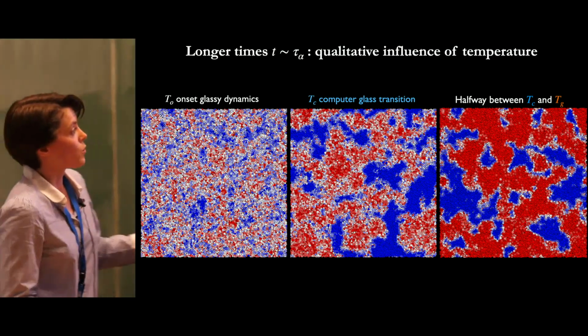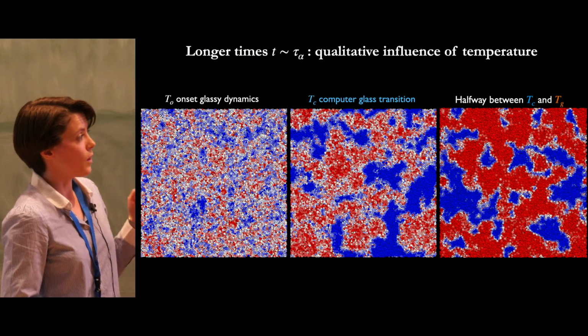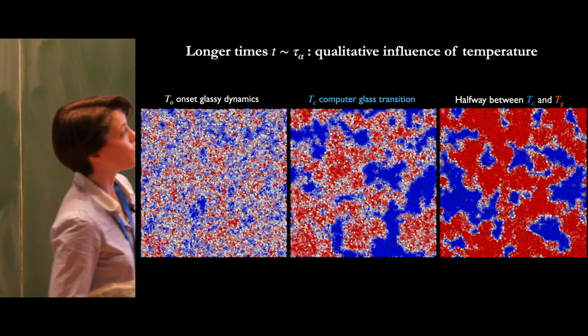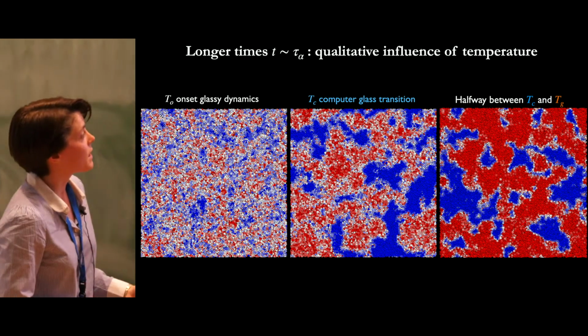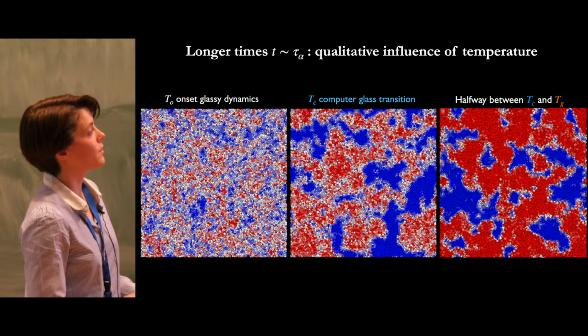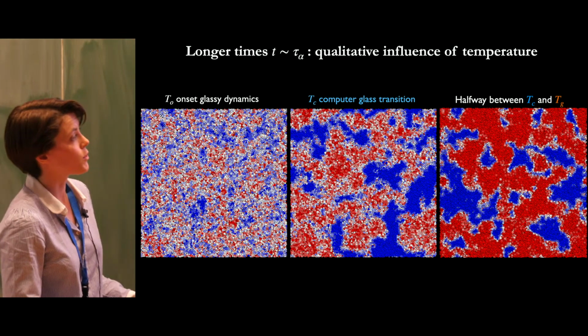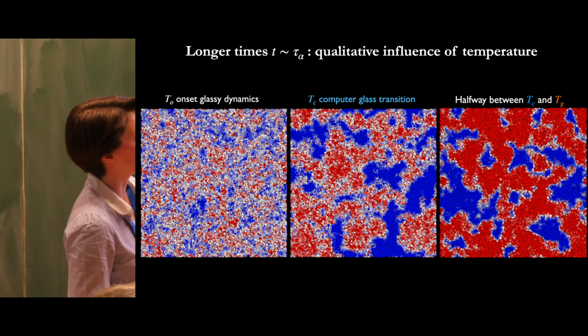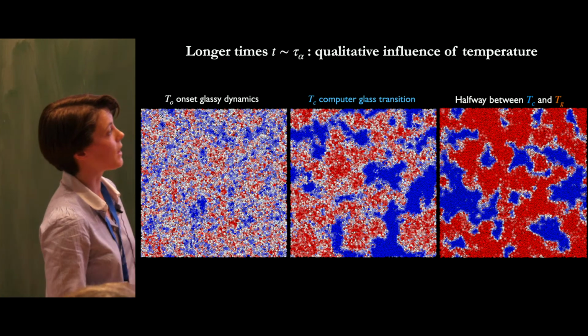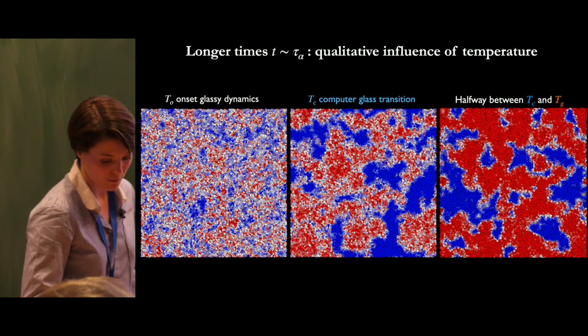So here again, I want to show you and give you an idea of what you get by going to much lower temperatures. At the onset, you don't see a very clear pattern, and then eventually at the lowest temperature where we can see 2 tau alpha, we see a very clear distinction between the regions that have relaxed in red and those that haven't relaxed.